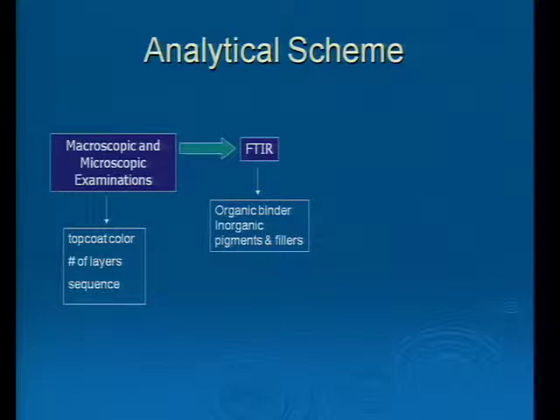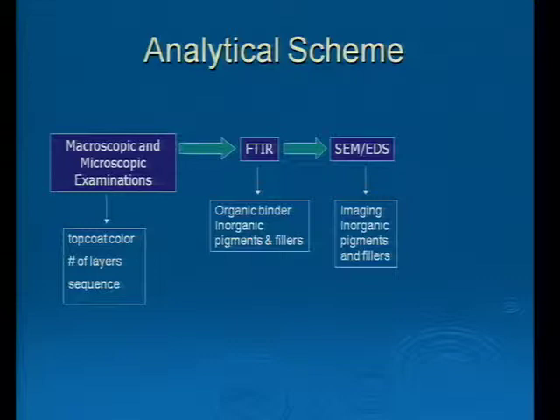We then went on to SEM EDS — both backscatter and EDS analysis — to image the samples, which proved quite helpful with some of the trickier layer structures, and also to assess inorganic pigments and fillers. And then finally on to PyGCMS, where we were confirming and in some cases differentiating the organic binders.